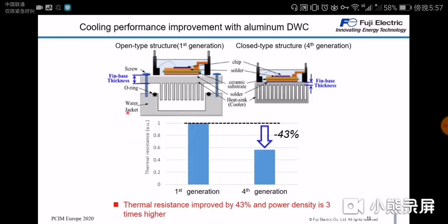Now we can see a simplified cross-section of our first generation water-cooled modules and our fourth generation water-cooled modules. The fin base thickness shown in here has been reduced a lot compared from the first to the fourth generation. In the first generation we had this conventional fin base thickness and the vertically aligned fins. They go down here into the water jacket. Then you have an O-ring around all of the water jacket, and then the top of the module is screwed down into the water jacket, squeezing these O-rings tight to get a waterproof connection.